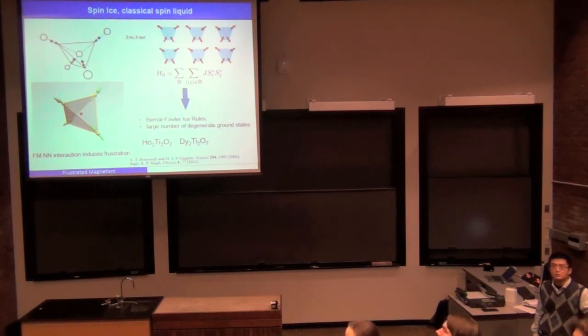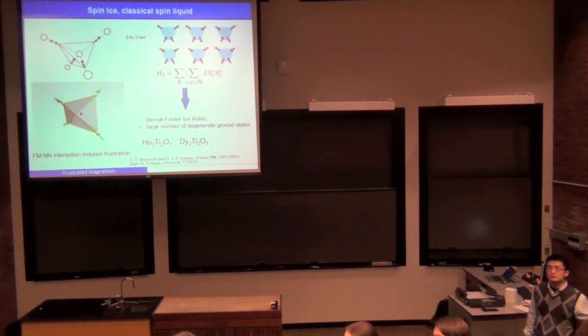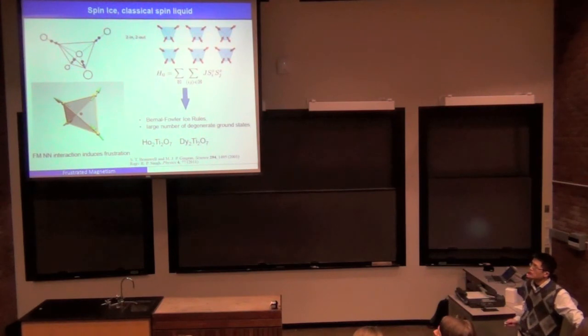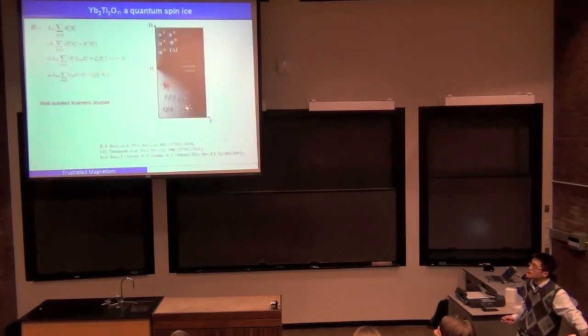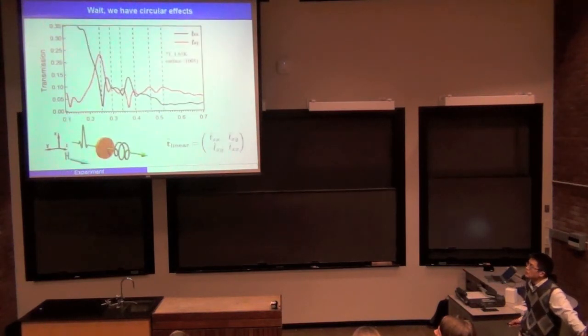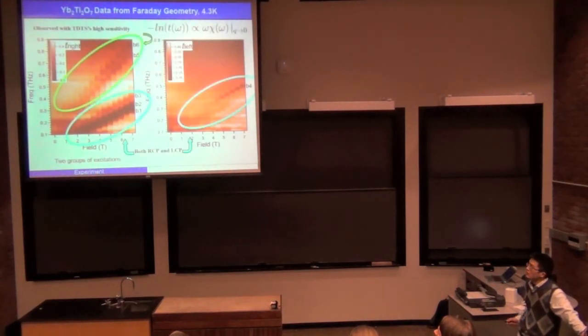Okay. I missed something. You mentioned something when you do some spin polarizing experiment, you double the frequency or something. I missed that particular part. Actually, I didn't mention frequency doubling, but in some of the experiments we see signatures of two modes of excitation. One group has about twice the energy of the other group. So this is basically a magnon, which corresponds to a single spin flip, and this group is of two-magnon nature, which corresponds to two spin flips. You may have been referring to the Terahertz polarimeter measurement. Oh, okay. Right.